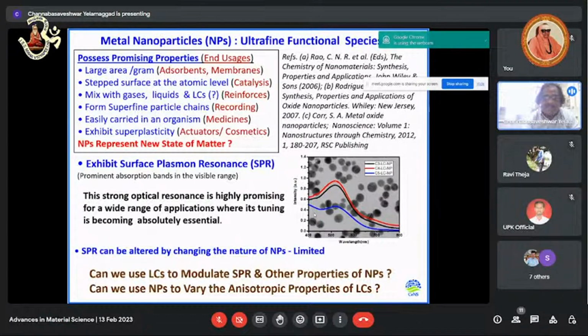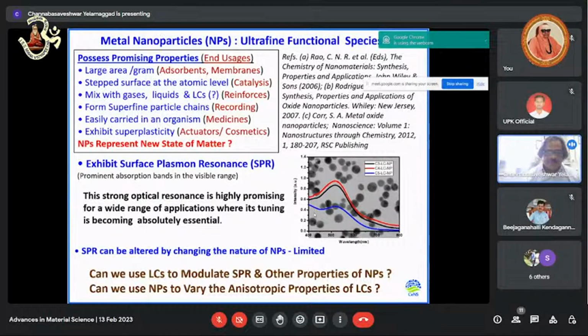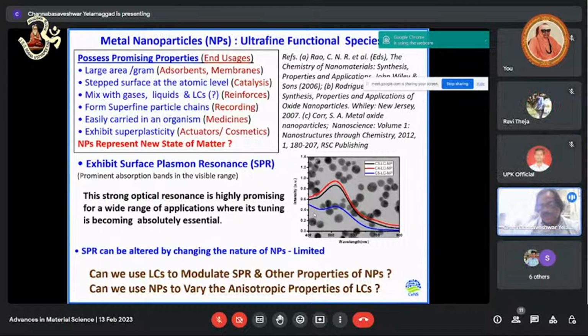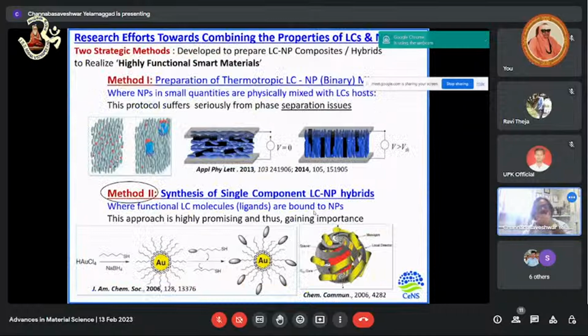And taking them to the liquid state is very, very important as far as the present technology is concerned. So the point was to see whether we can shift the SPR peak, which you can clearly see in UV. Can we shift the lambda max from 500 nanometer to 600 or 700, something like that? Looking into that aspect, we tried to coat them with liquid crystals to see whether we can drift it. So there are some ways.